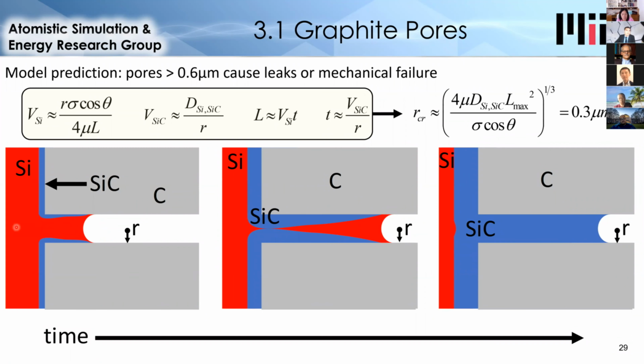So silicon is pulled through the pore by capillary forces much more strongly than gravity pushes it, because the pores are small and silicon wets graphite. And so that was the main driving force for the silicon flow, which is indicated by the first equation, looking at the velocity of silicon, which is driven by surface tension and resisted by viscosity.